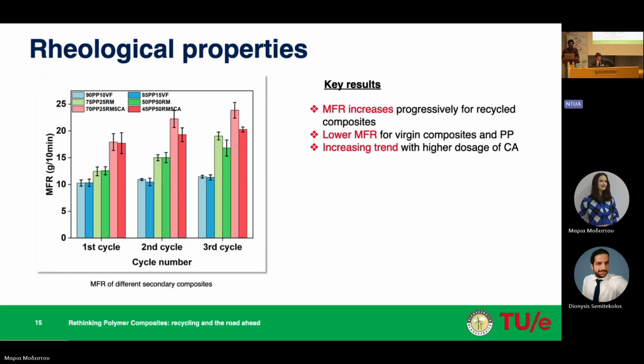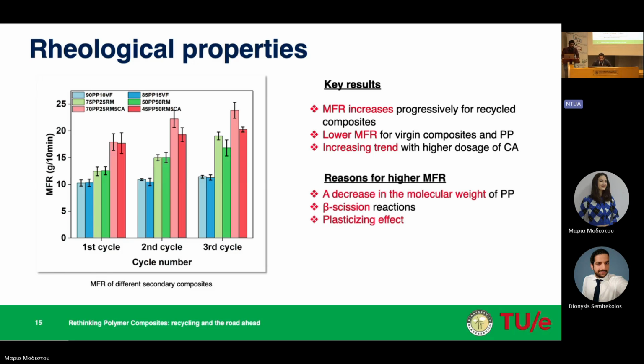And also, we can see that there was an increasing trend for recycled composites with coupling agent. But there are also quite a few reasons behind this. One is that, obviously, after the reprocessing, the molecular weight of polypropylene would eventually decrease, which enhances the melt flow rate of the composites. And also, there is a possibility of beta scission reactions happening in polymer chains, which actually cut the long chains of polypropylene into shorter chains, which will eventually increase the melt flow